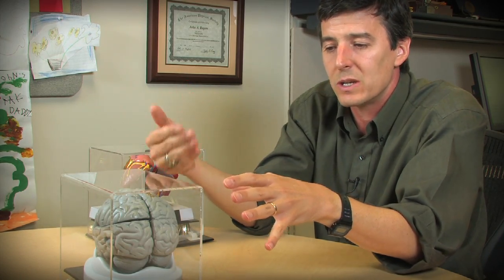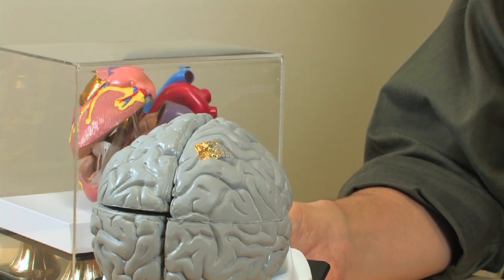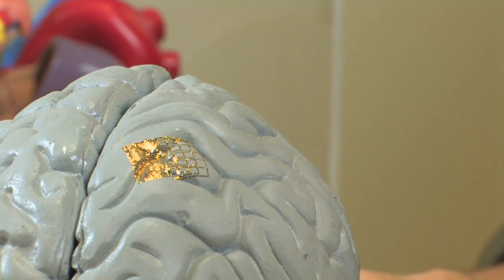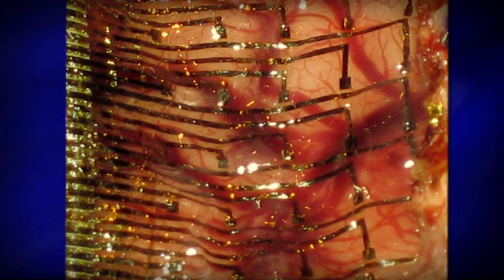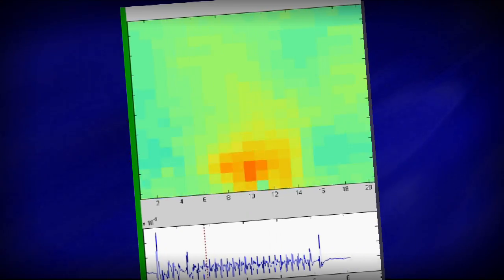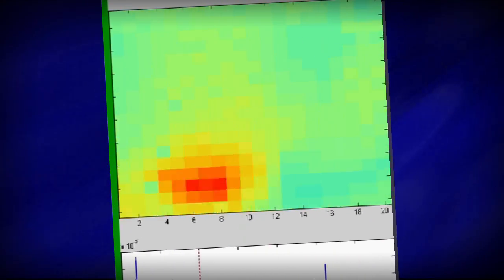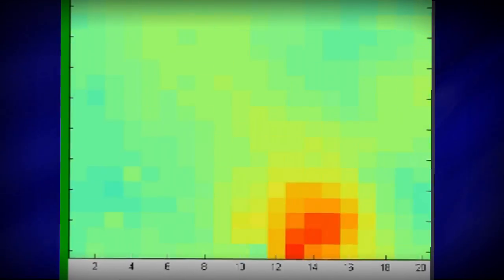That water dissolves the silk, which is a water-soluble class of material. It's also bioresorbable, so the dissolved silk flows into the brain cavity but over time is resorbed by the body, making it completely non-invasive. When the silk has washed away, it leaves behind an ultra-thin form of circuit technology floppy enough to conform to the contours of the brain, establishing an interface that allows very high resolution mapping of electrical processes in the brain — offering unprecedented capabilities to a surgeon trying to locate abnormalities for a subsequent therapeutic procedure.